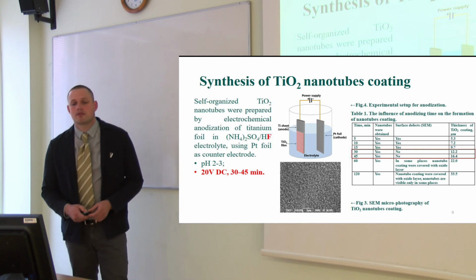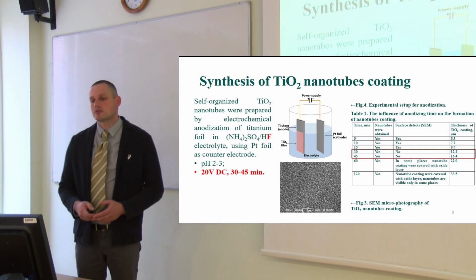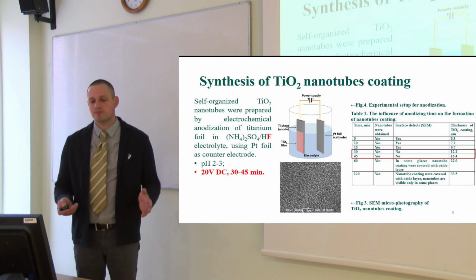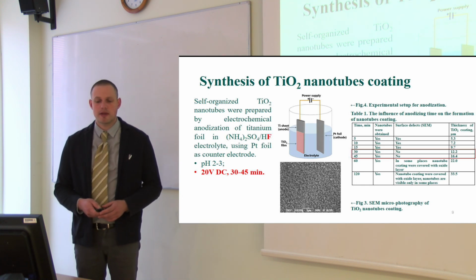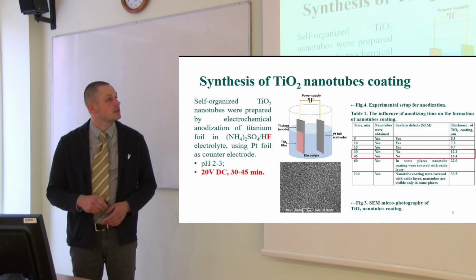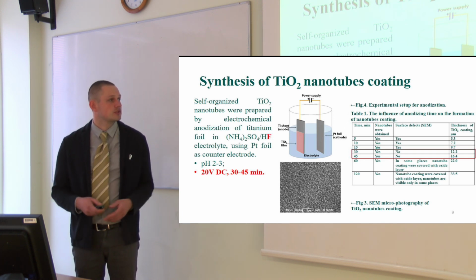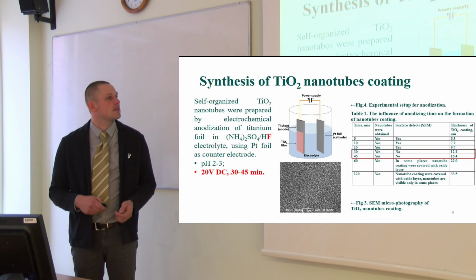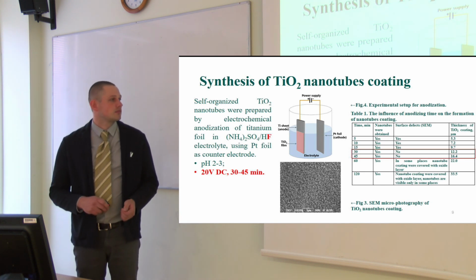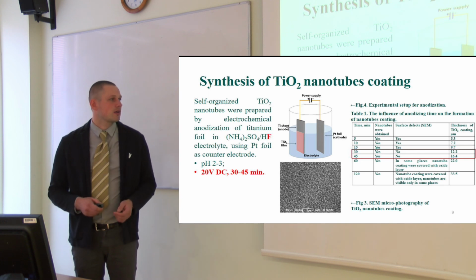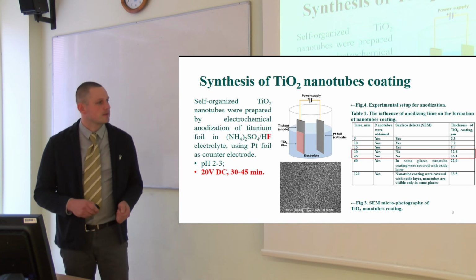So the first method for obtaining nanostructures was chosen anodization. It is an electrochemical method, so we use titanium foil or sheets. The second electrode is platinum. We have an electrolyte containing fluoride ions. The electrolyte can also be other, let's say, electrolytes, but it is important to have fluoride ions here.